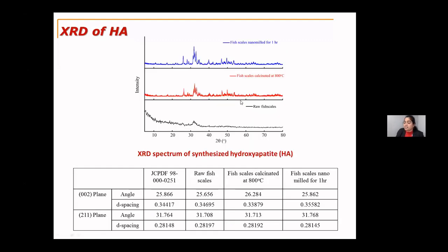And then further, we characterized using X-ray diffraction spectrometry. So for this, I chose to show the raw fish scales, which is the bottom one. As discussed earlier, the raw fish scales have carbon content, then proteins, fats, lipids, collagen, and many other particles along with the hydroxyapatite. So the hydroxyapatite peaks were not shown clearly for the raw fish scales because it includes all the other materials too. But when the fish scales were calcinated at 800 degrees centigrade, the hydroxyapatite shows up.